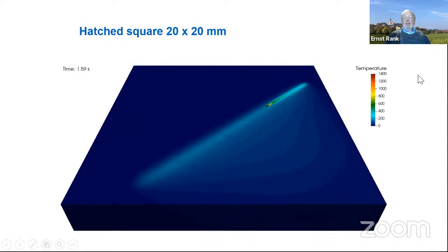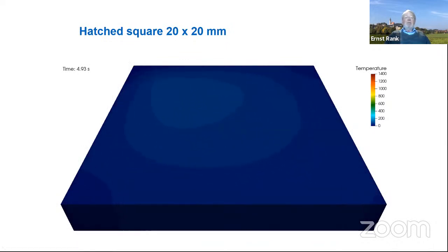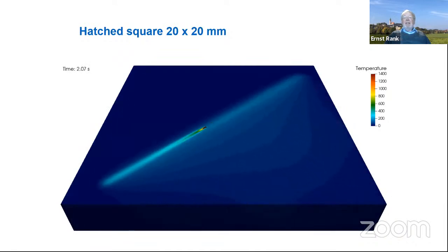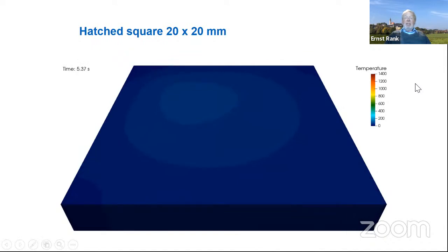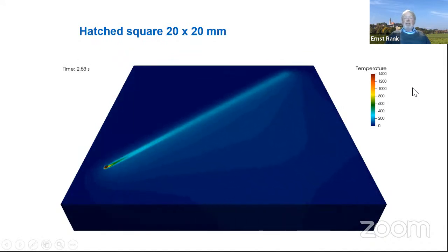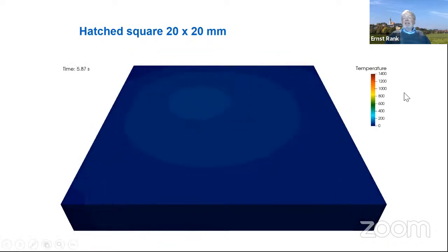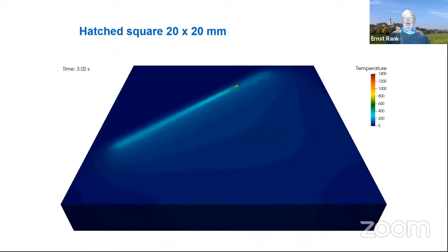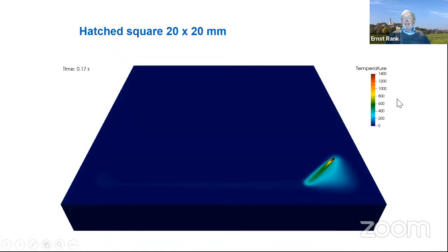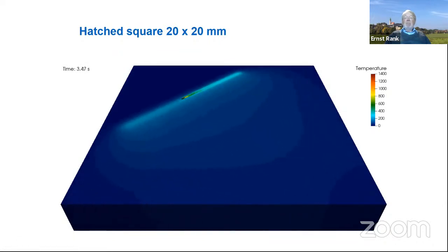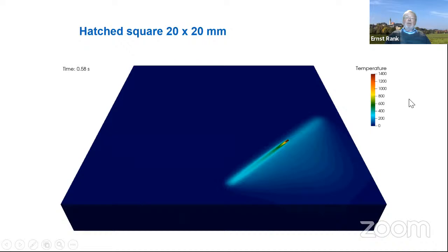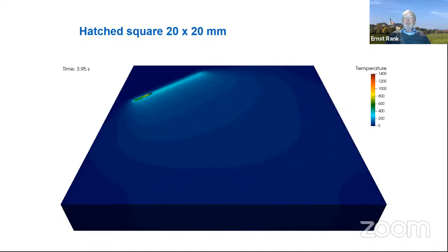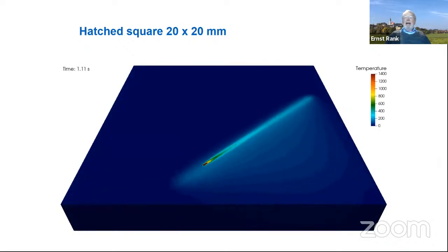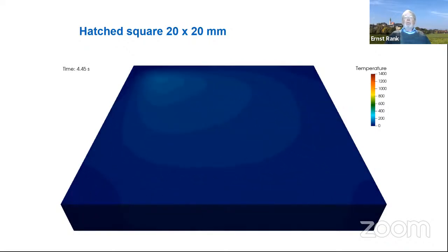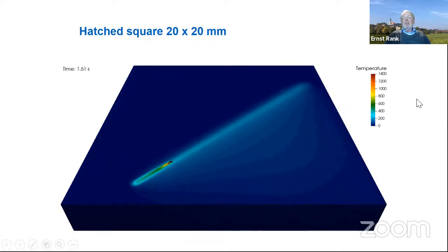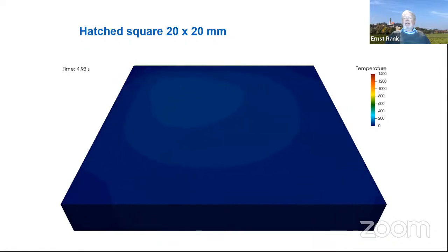Okay, so well, what you see here, this would be in real time. So this is the process, this is really about 6 seconds. The computation time, and this is still on a powerful workstation, I would say, one CPU, is still in the order of 10 to 15 hours. So still quite a significant time which we are having here for this problem. But, and as I said, it's work in progress. We are going now to real high performance computing, where we expect that we come down to, well, minutes for this simulation, where really the physics is resolved in this scale from melt pool to the layer.